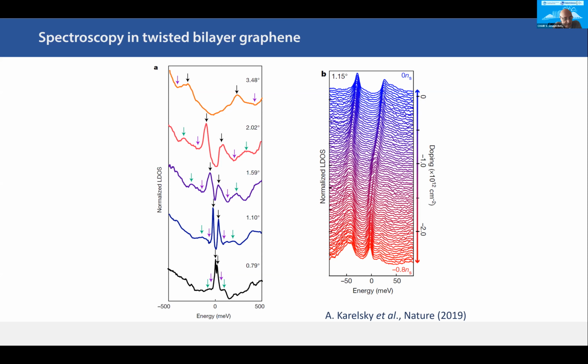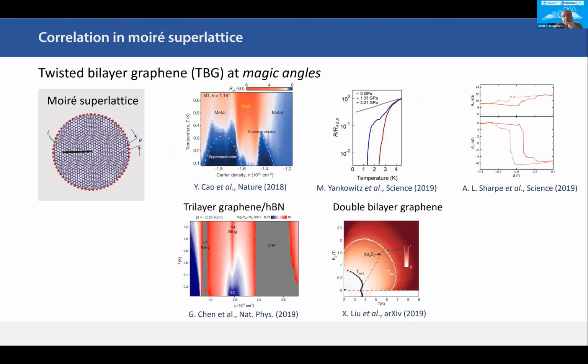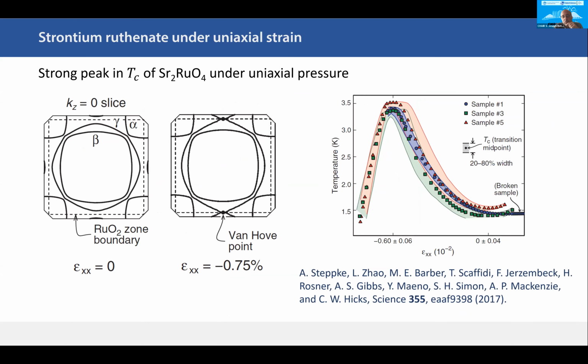Probably in twisted bilayer graphene, this analysis is fine in the sense that you have these scale invariant Fermi surfaces, but in other materials that are more complicated, with more bands, probably everything will be important, in the sense that you then have scattering from other parts of the Fermi surface. In strontium ruthenate, certainly this is something that is happening, that other parts also play a role, and therefore Kohn-Luttinger superconductivity, for instance, may be seen elsewhere. Yes, I agree with you.